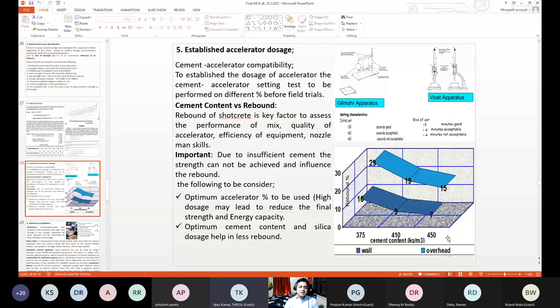If your cement content is lesser, 375 kg, then your wall rebound will be 16% and your overhead may be 29%. It is not a Bible, but it is statistics from the manufacturer or some industry expert. But you can do a better mix design with the appropriate materials, and you can establish your own cement content and how much rebound and wastage you find on that design.